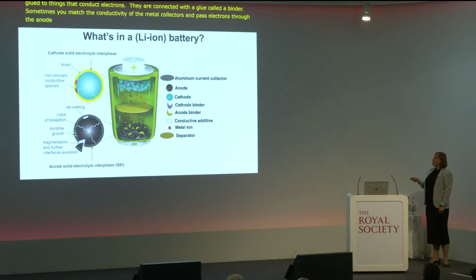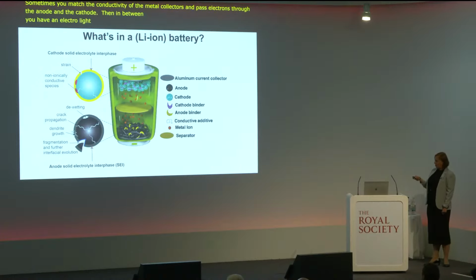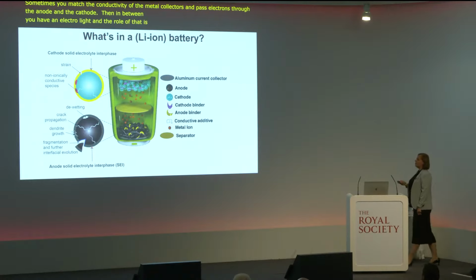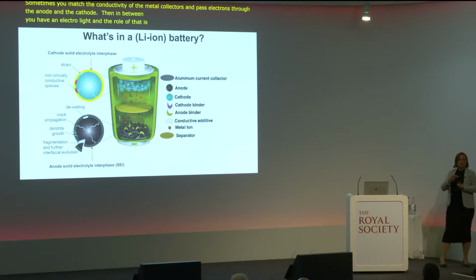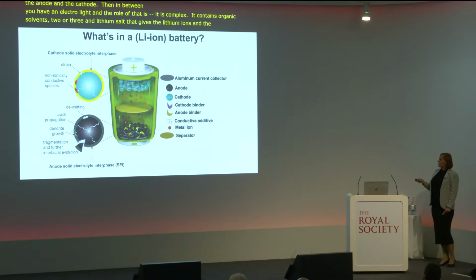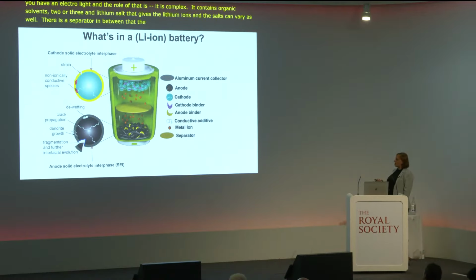And then in between, you have an electrolyte. The role of the electrolyte is to transport ions between anode and cathode, but not electrons, because they have to go on the external circuit. The electrolyte itself is complex, and it contains organic solvents, sometimes 2 or 3, and a lithium salt that gives the lithium ions, and these salts can vary as well. There is a separator as well in between that the ions go through, and as you charge and discharge the battery, there's a lot of complicated processes happening.